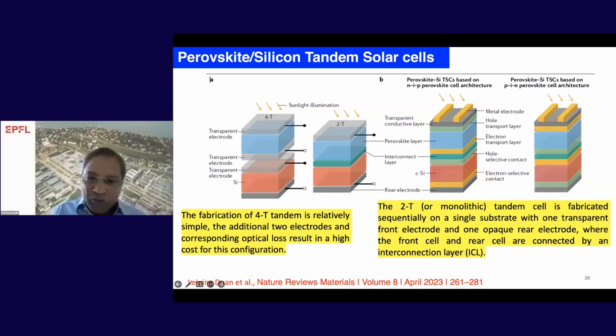So let me take the two-terminal configuration as shown here. The bottom is a silicon solar cell and the top is a perovskite layer, and in between we have an interconnection layer. After the interconnecting layer, if we put the electron transport layer followed by the perovskite and hole transporting material, then this is a NIP configuration on top of the silicon solar cell. Similarly, we can also change this: the interconnecting layer followed by the hole transporting material. This hole transporting material is very popular here. Many groups are using SAMs, self-assembled monolayers, which I showed you as 2-PACz and 4-PACz. These are carbazole-containing phosphonic acid groups, which self-assemble on top of the recombination layer, followed by the perovskite. The ETL layer is C60, and then we have a contact. So these are very interesting topics.